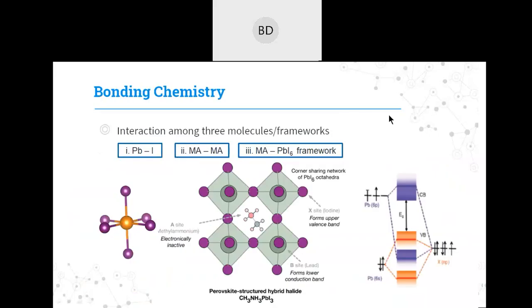Before understanding the degradation mechanism of the perovskite, first we have to understand the bonding chemistry of the perovskite. The bonding in the perovskite structure is basically considered as the interaction among three components. The first one is the interaction between lead and iodine, which is governed by a partial ionic, partial covalent bond. The second one is the interaction between this methyl ammonium and the nearby methyl ammonium, which is governed by dipole-dipole interaction. The third one is the interaction between the methyl ammonium and the PbI6 octahedra, which is governed by hydrogen bonding. So overall, there are three types of bonding present in the perovskite: the partial ionic, partial covalent character, the dipole-dipole interaction, and the hydrogen bonding.